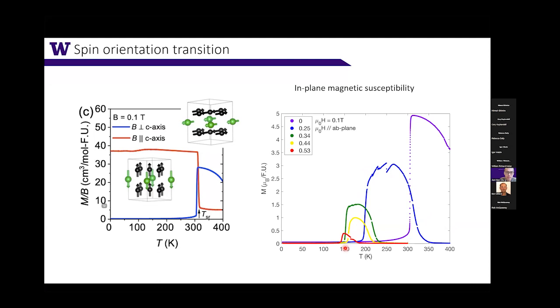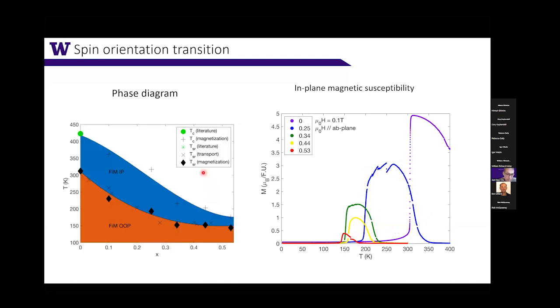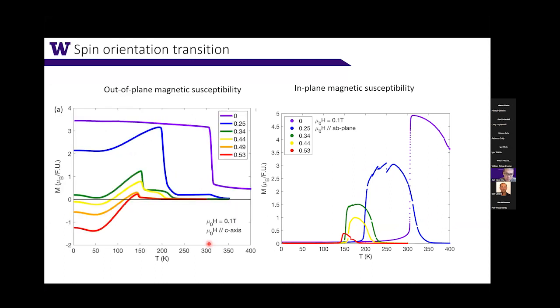Based on this, you can create a phase diagram where the ferromagnetic transition temperature and the spin orientation temperature are progressively suppressed by x. So everything seems to be what is expected. However, if you look at the out-of-plane magnetization, something quite interesting happens.